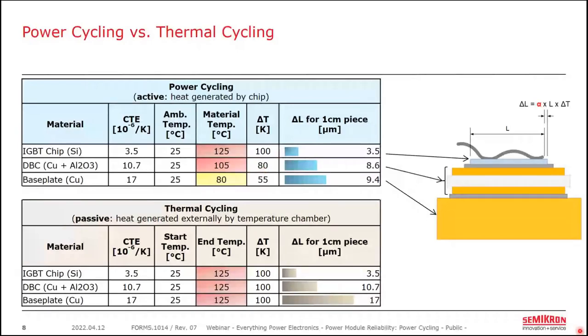So let's contrast that concept with thermal cycling, where an unpowered module is placed in a temperature chamber and it is then heated and cooled by means of the temperature chamber itself. So you would start at a 25 degrees Celsius ambient and then heat up the oven and wait until thermal equilibrium was achieved across the entire module. And this means that all of the materials are seeing the same delta T. In this case, that's fine for the IGBT since it's seeing the same 100 Kelvin rise in temperature as it did in the power cycling test.